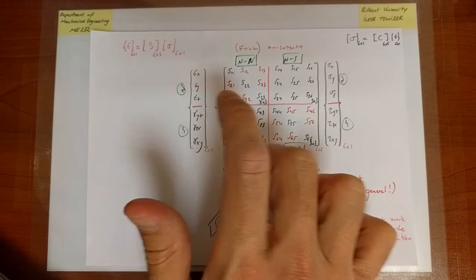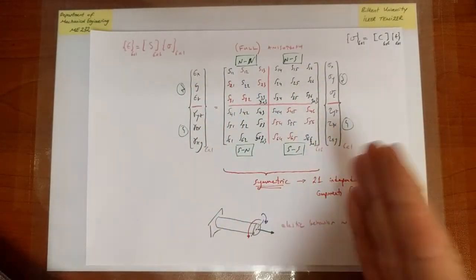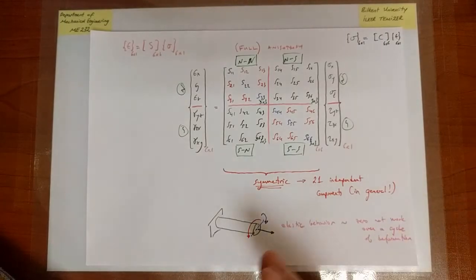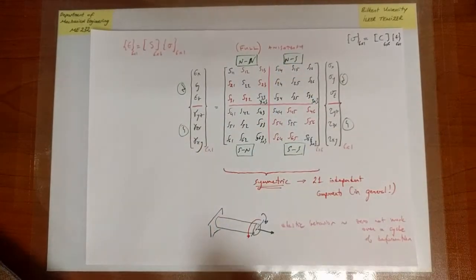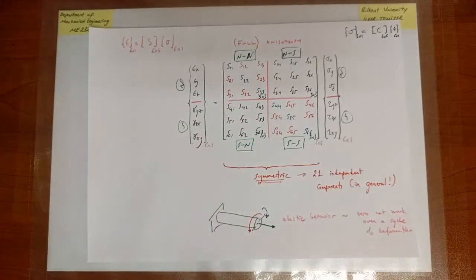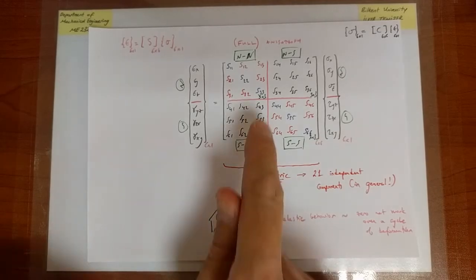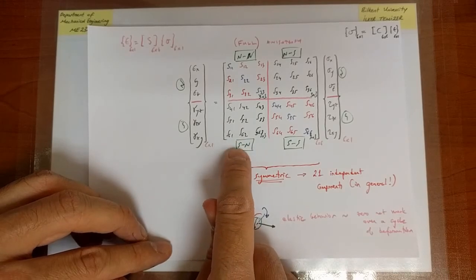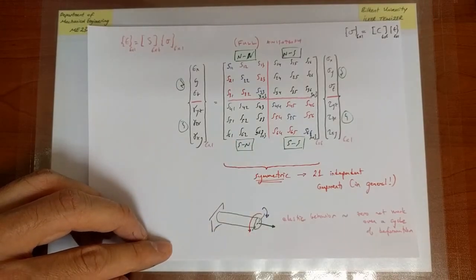If it's not, you apply a stress, you get a deformation, and you keep calculating the amount of incremental work you do. You sum them up over a cycle. If this is not symmetric, you'll end up with a net work. Where did that work go? Well, it's unphysical. That's not something you expect, and therefore the matrix needs to be symmetric. And that's why if a material, an anisotropic material, displays normal shear coupling, you expect it to display shear normal coupling as well. All right.